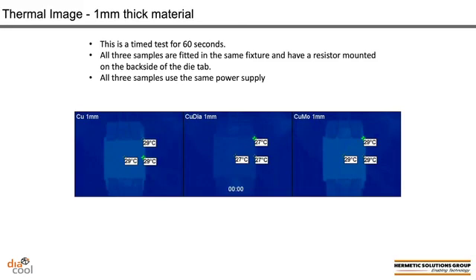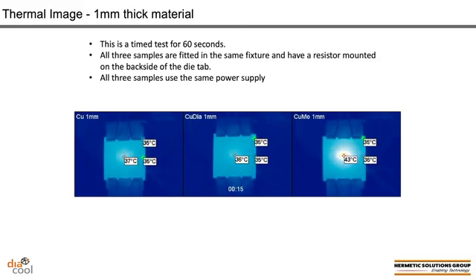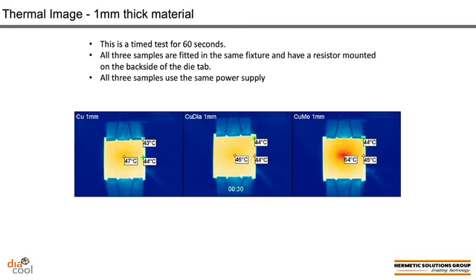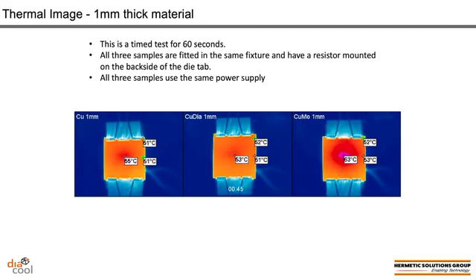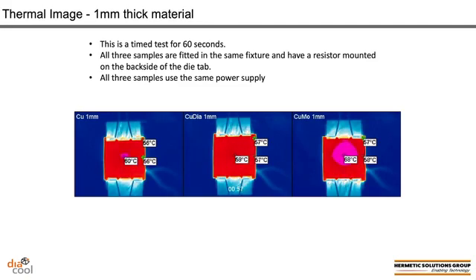Now what we're going to do here in this test is we're going to fire up those resistors on the back side of these substrates and take a thermal image of the three substrates of material and see how they manage that heat flux generated by the resistor. So you can see the temperature starting to rise. You start to see a significant hotspot develop on the copper moly sample. And now you can see a large hotspot appear in the copper sample.